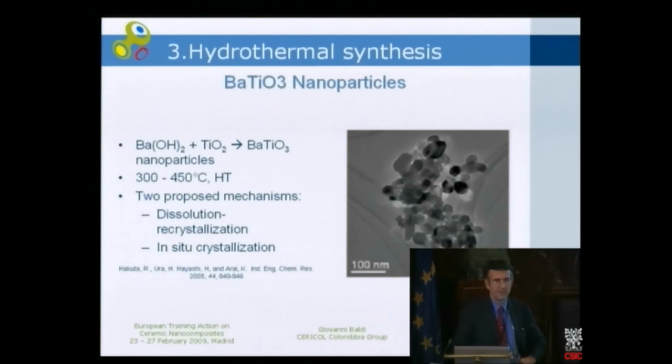This is an example of hydrothermal synthesis of barium titanate nanoparticles, which at 300 to 450 degrees are produced as very thin and quite regular nanoparticles of barium titanate.